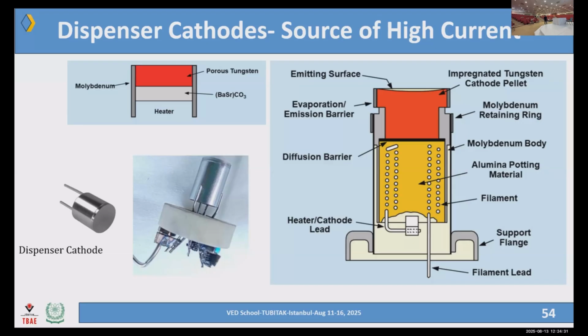Usually, when people were working with cathodes, they used oxide-based cathodes. Once those cathodes are exposed to air, they are finished. They cannot be regenerated. The chemistry cannot be redone. This is not a reversible process. But here, if some accident happens, unless you just burn the cathode right away or break it to a point where you cannot do something.